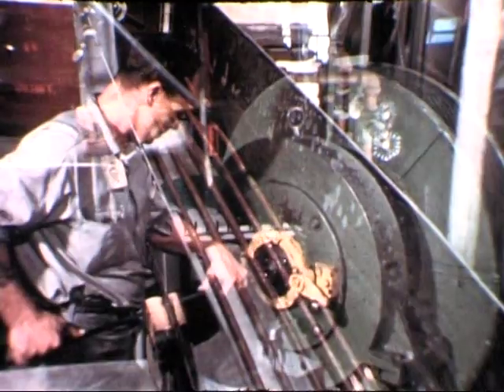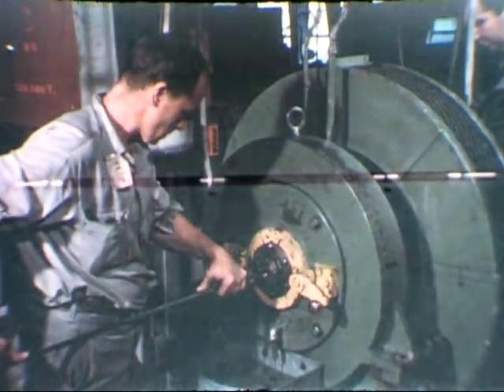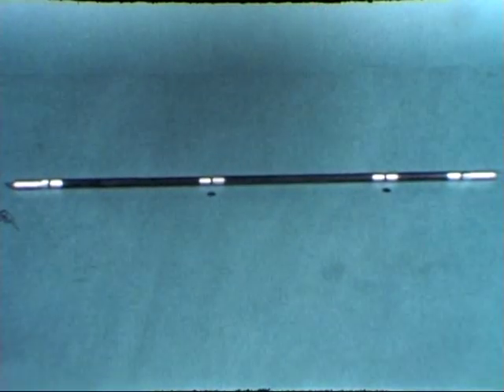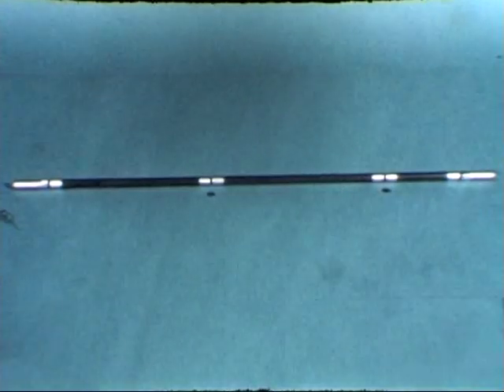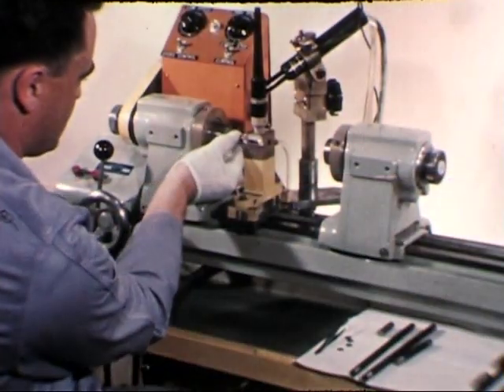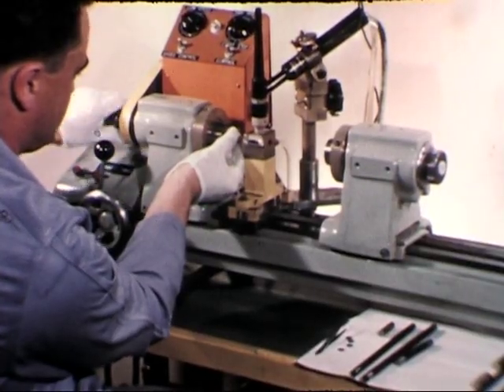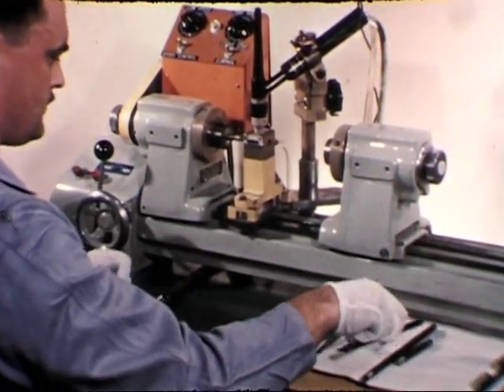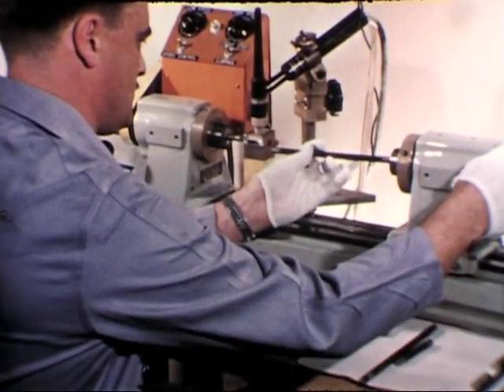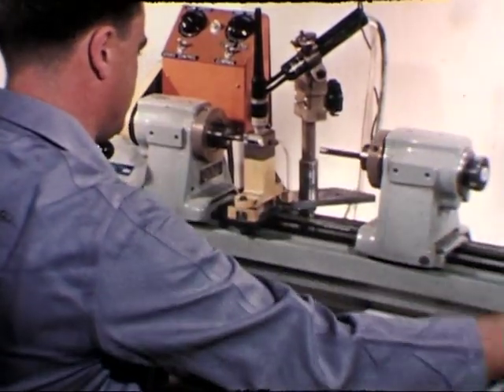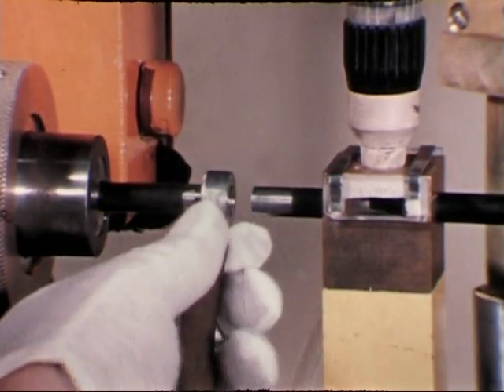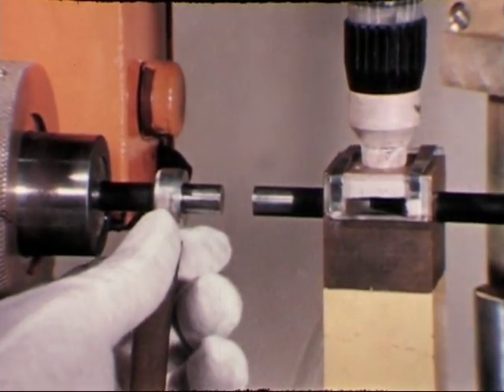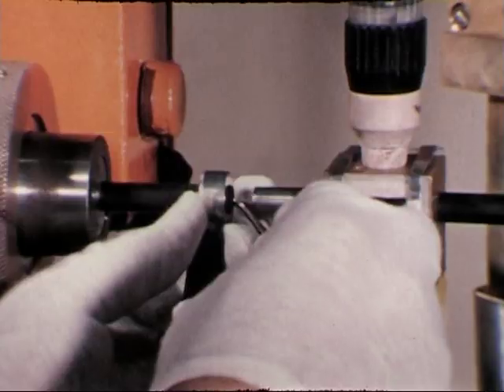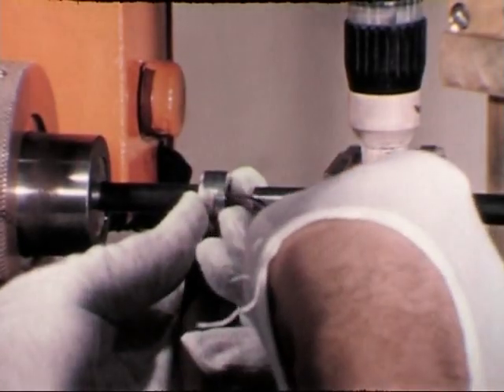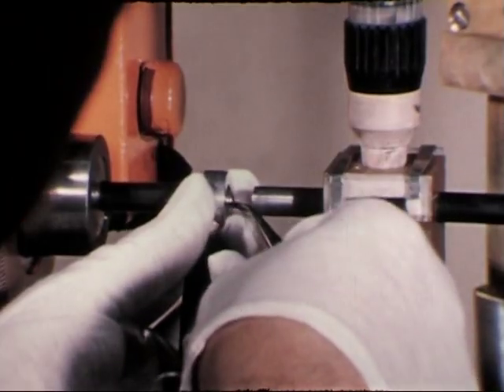Upon return, they are inspected, pickled to remove the copper, and swaged to a specified diameter. Heat treated for stabilization, the rods are cut to appropriate fuel and blanket lengths, and the cladding thickness measured. To join the sections of either type rod, a commercial glass lathe was specifically adapted at Argonne for tungsten arc butt welding. This welding operation is extremely precise because of the difficulty of fusing the high melting zircaloy without excessive melting of the uranium. A 10 mil zirconium spacer disc separates the enriched and blanket sections on each fuel rod.